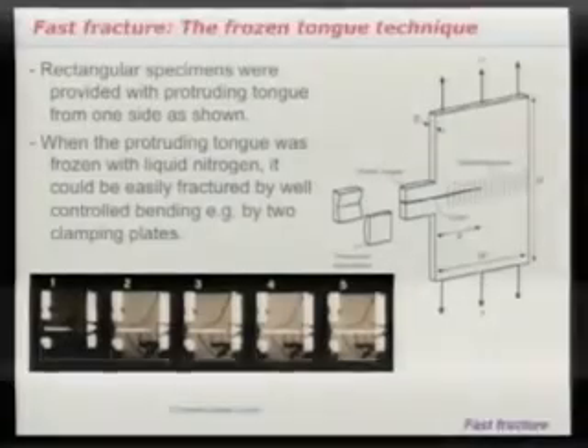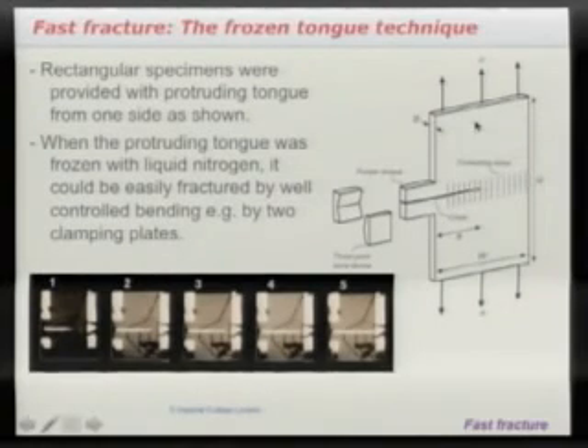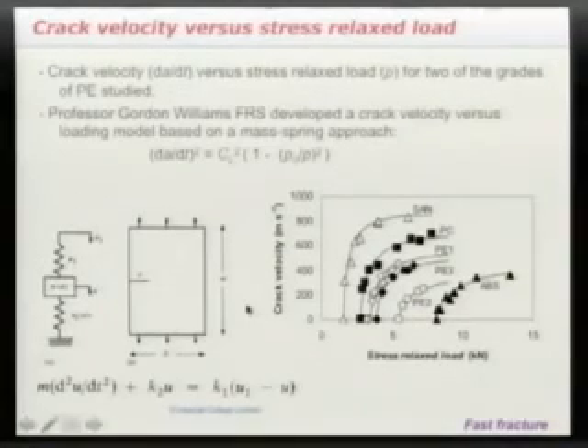Okay, so the principle of this, let me go back to the slide. You can see you initiate the crack in the tongue section, and the crack then runs in, and depending on the loading condition, if the load in here is quite modest, the crack will run in and arrest. But if you've got sufficient load in the main section, the crack will then run all the way through. And in fact, we used an Imacon camera in those days. It used to produce a series of pictures on a Polaroid back.